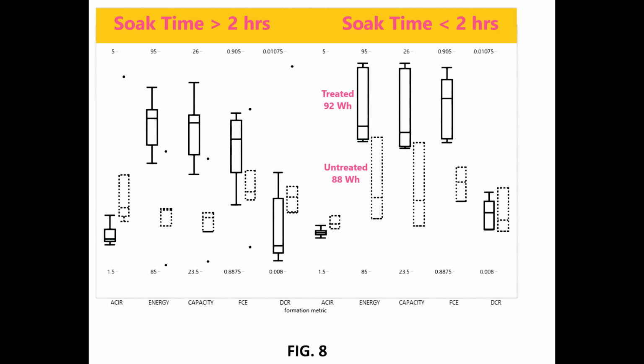It dramatically improves the cycle life of the battery cell, but it does chew up some of the lithium, which slightly reduces the energy density. Figure 8 shows that plasma-treated battery cells soaked for less than 2 hours in electrolyte unexpectedly saw a performance improvement over untreated cells. The finished cell energy increased from 88 to 92 watt-hours, which is about a 4% energy density improvement. Tesla didn't provide any more information than that, and it's quite a surprising improvement.